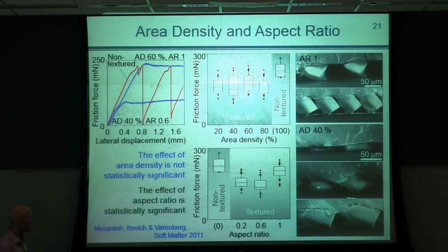And somewhere in the middle, there exist several geometries where the stiffness of these projections is not large and not low, and they do not fall aside, they are not able to maintain the initial shape, they just stand on a corner, which results in the lowest possible friction, and we can see it here. So it was found that aspect ratio is the main parameter that determines the system response.